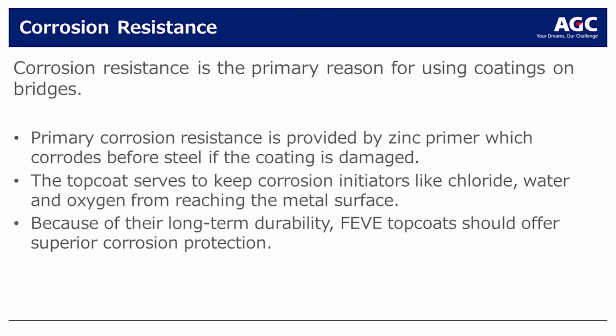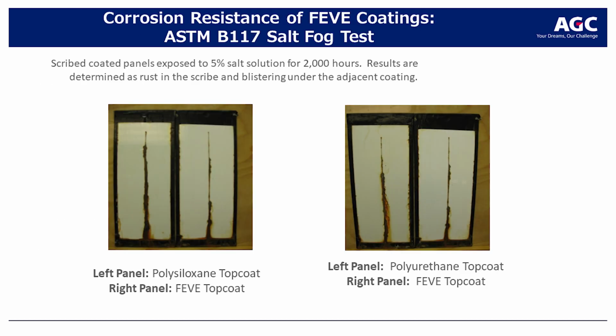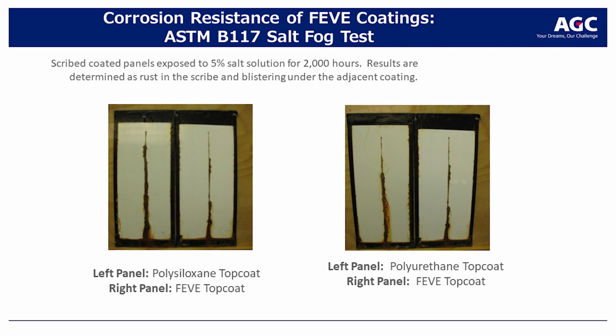And this is a specific test, if you've done this or looked at this, the ASTM B117. We took a high performance polysiloxane, and we also took a high performance polyurethane top coat, and we compared them on panels to what a Lumiflon based FEVE coating system would look like. This is just the top layer. So we scribed that top layer and opened it up and said, hey, corrosion, go ahead and start. And this really is testing how good the panel is at resisting.